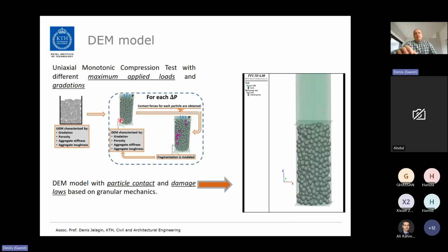This is how the procedure looks. It is, of course, incremental. We have all our input parameters in our discrete element model: gradation, porosity, aggregate stiffness, and aggregate fracture toughness coming through contact and damage laws. And then in each force increment, we extract contact forces at aggregate-to-aggregate contact pairs and compare them with our failure law. At a certain point, when a given aggregate reaches its strength, we end up with fracture of the material, and the cracked aggregate is illustrated by making it pink. And as you will see here in a second, when an aggregate breaks, it also affects the overall macro-scale response of the material, because the bearing capacity of broken aggregates is compromised, so the material can settle further down in the structure.